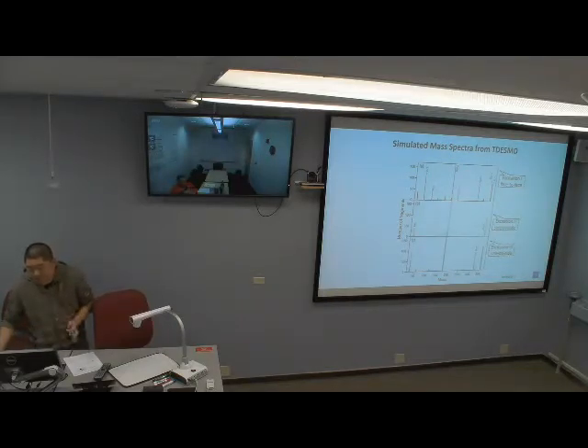In addition to the monomer peak and the dimer peak, we also observe other species. The species at the left correspond to fragments with molecular weight less than the monomer, and the species at the right correspond to fragments with molecular weight higher than the monomer. So basically, this part can be understood as fragmentation, and this part can be taken as polymerization.